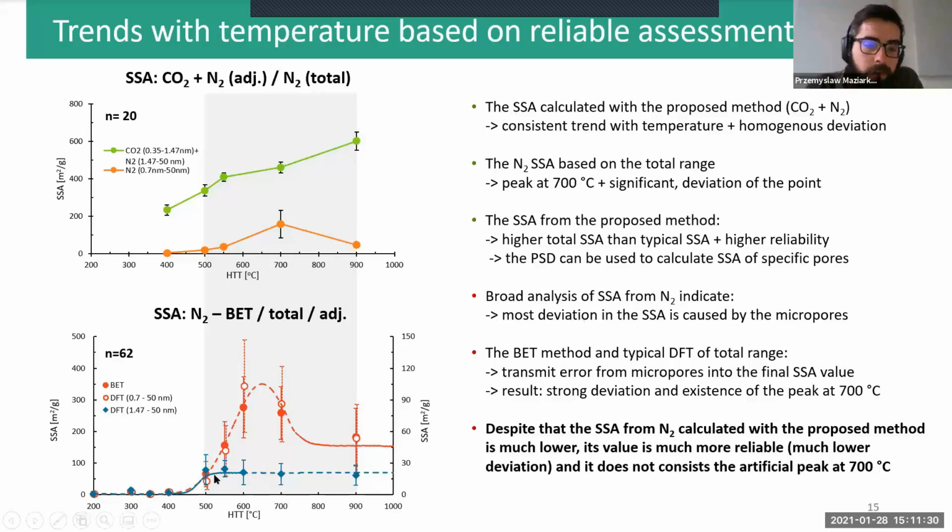On the other hand, when we use the adjusted method, then we can observe homogeneous deviation and a very consistent trend. And as well, we do not see this artificial peak, which presumably is caused by the adsorption stress and the structure being prone to undergo pore structure change.